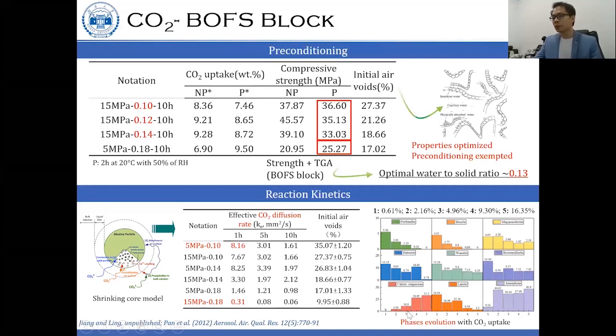And we're also using QXRD to quantify the phases, and we will see the evolution with different CO2 uptake. Sample 1 refers to the lowest CO2 reactivity. Sample 5 refers to the highest CO2 reactivity. As we can see, there is a reduction of portlandite and brucite phases if we increase the CO2 reactivity. And as we increase the CO2 reactivity, we also found that the calcite, magnesium, and amorphous phases have increased.